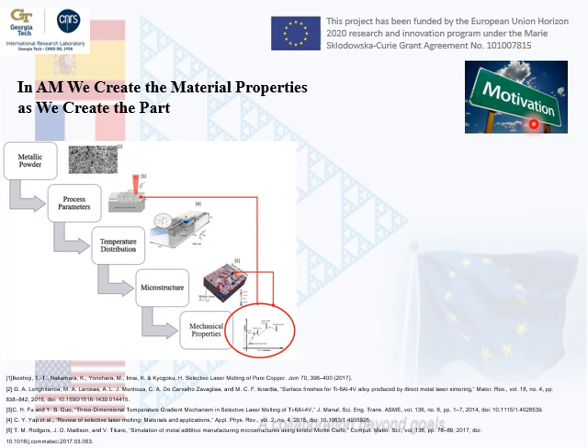Nevertheless, as would be the case also for conventional materials, controlling the microstructure during the processing is fundamental, since this also allows controlling the final properties of the material by means of the microstructure itself. And in this task, simulation can be very helpful, right? Because simply by changing the parameters of the simulation, the processing parameters in the experiment, we can also realize many different microstructures, right? And because there's always a connection between the simulations and the experimentation, we expect that these predictions are a faithful reproduction of what we can expect from the experiment, right?